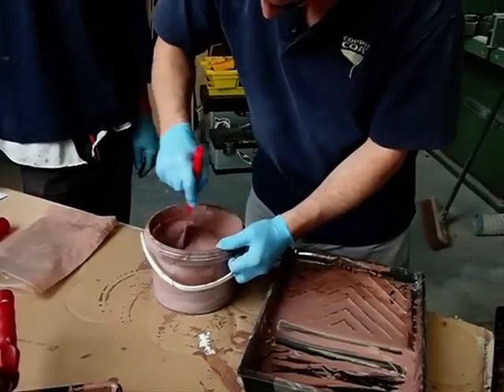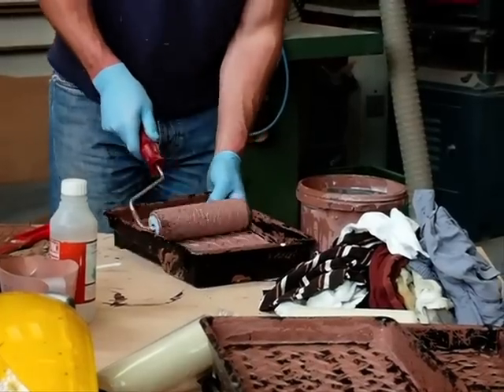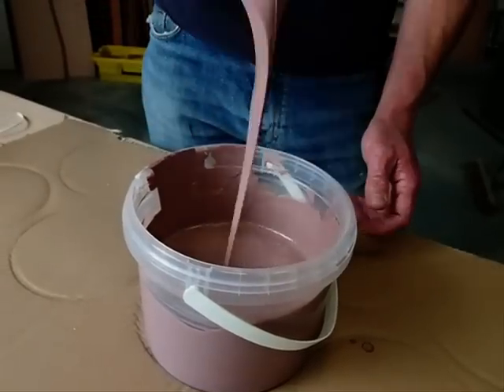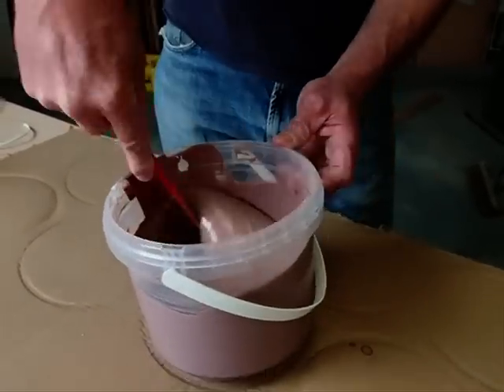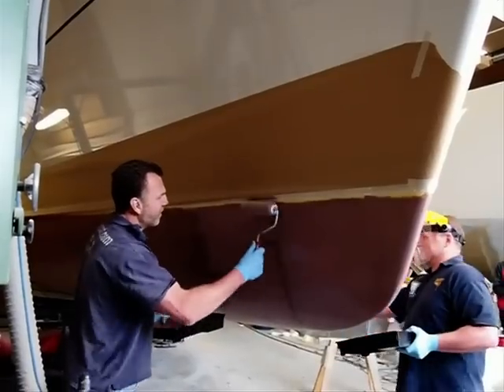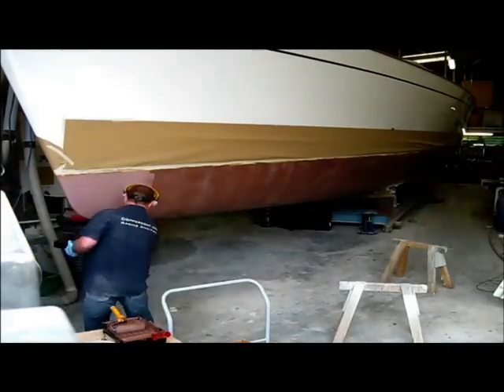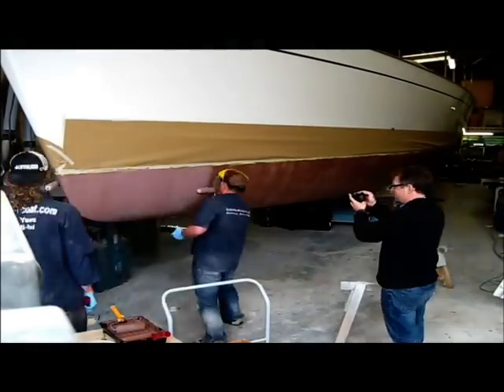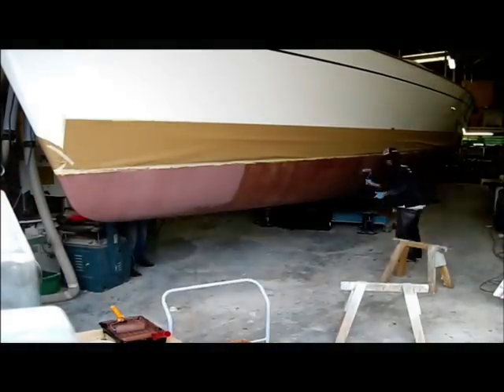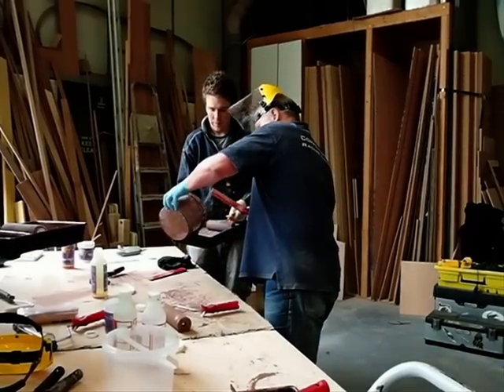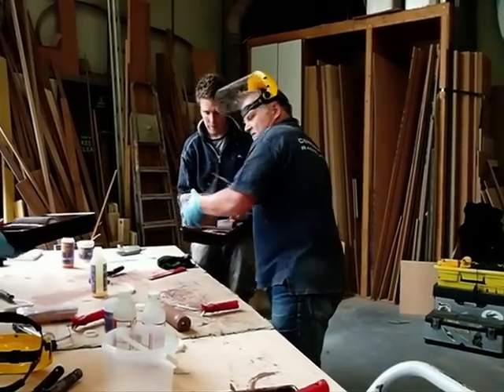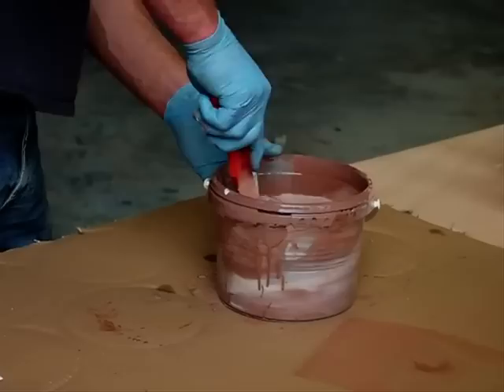As a guide, the mixed pot life of Coppercoat is approximately 40 minutes at 20 degrees centigrade. Though with 2 people applying the product with large rollers, a 1 litre unit will usually be applied within half that time. As with most epoxies, the pot life shortens as the ambient temperature rises. Therefore, be especially careful not to prepare too much Coppercoat in one go when working in high temperatures.